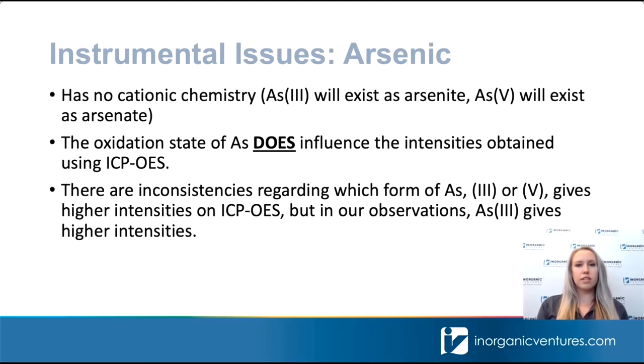When we think about arsenic in solution, we may think of arsenic 3 and arsenic 5 as arsenic plus 3 and arsenic plus 5, but arsenic actually has no cationic chemistry. So arsenic 3 in solution is going to be arsenite, and arsenic 5 in solution is going to be arsenate. So the oxidation state of arsenic does make a difference in your ICP-OES analysis, as these two forms in solution will give different intensities on the instrument.